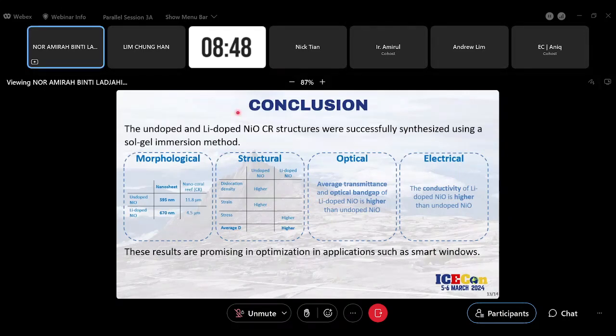So for undoped and lithium nickel oxide structure was successfully synthesized using a sol gel immersion method. There are significant difference exist between both samples regarding to their properties. As I mentioned before, I use the thickness of the nanosheet to run other properties. For morphological, as I said before, the lithium doped nickel oxide is thicker than undoped nickel oxide sample. For structural properties, the average crystallite size for lithium is larger than undoped one. This is the result.